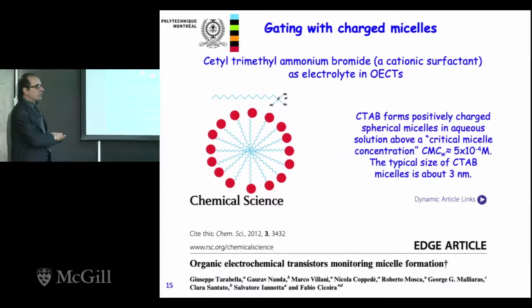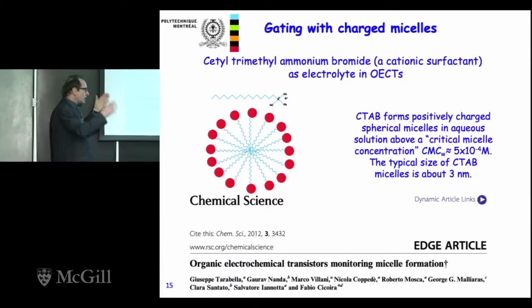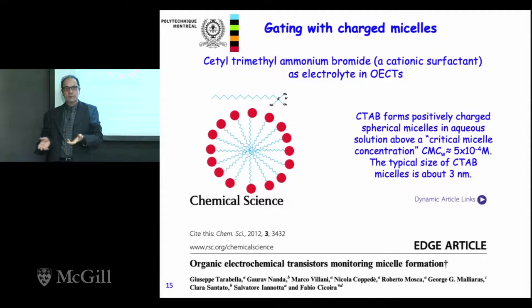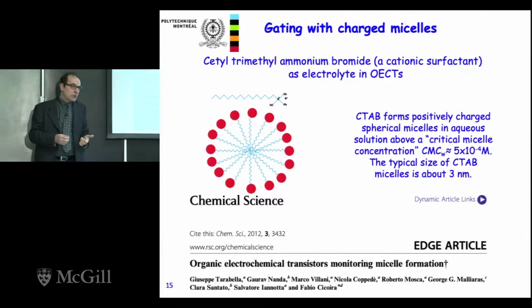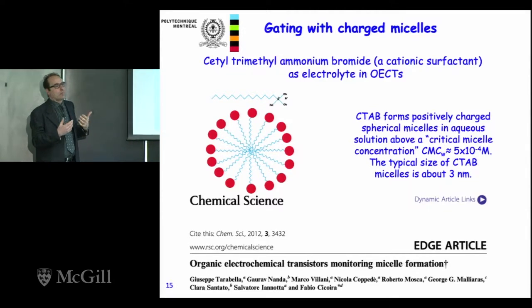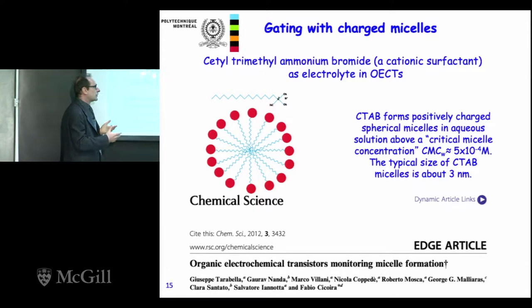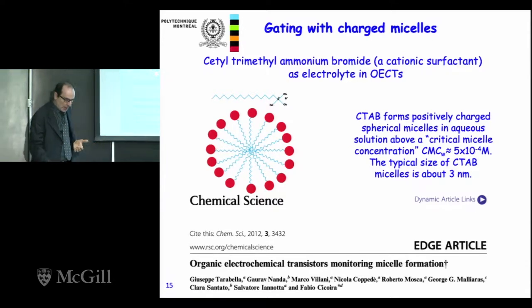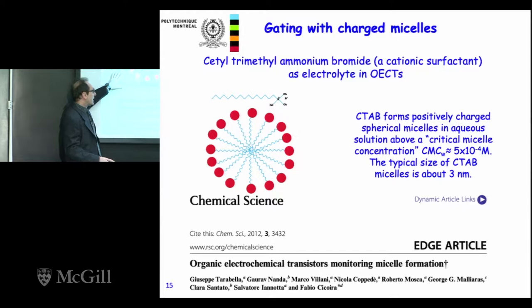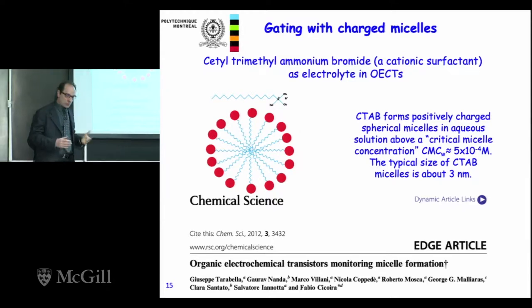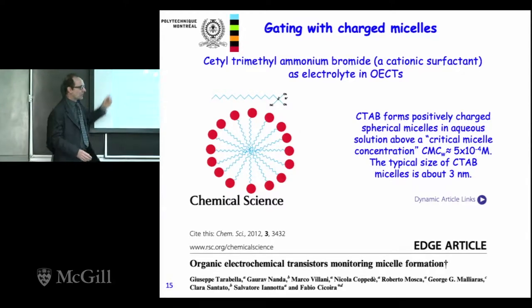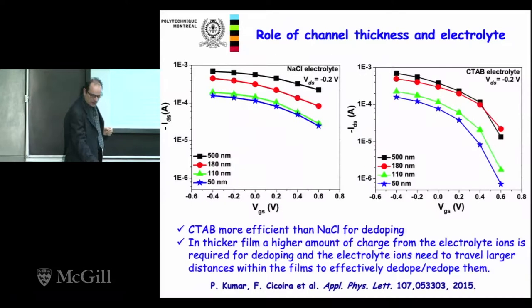Then this is something on the effect of the electrolyte. You have seen in my picture of the working mechanism of the device, you have an electrolyte. And of course, the performance of this transistor depends on which electrolyte you have in this solution. And we found out that one of the electrolytes that work best to have a good transistor performance is a cationic surfactant. Here I have an example.